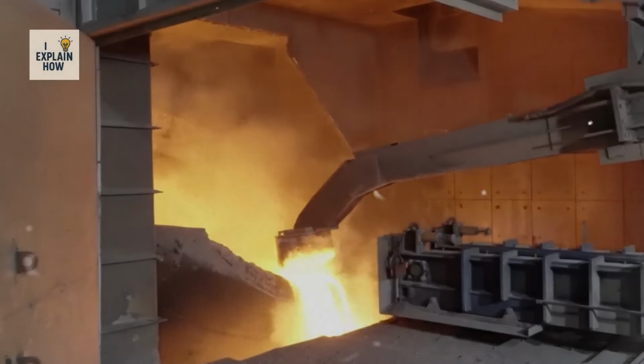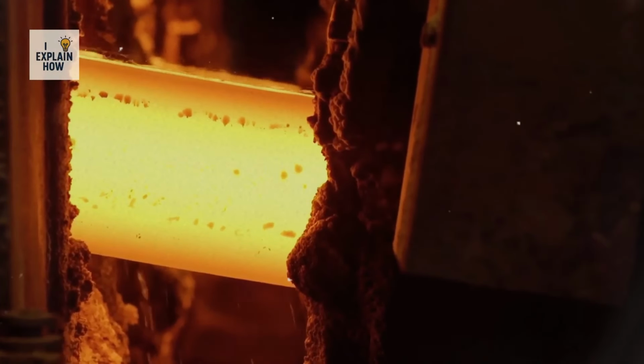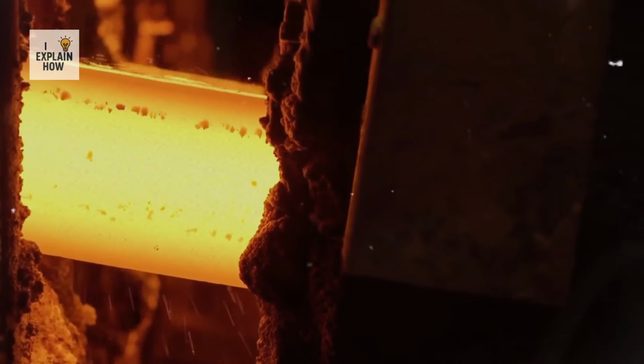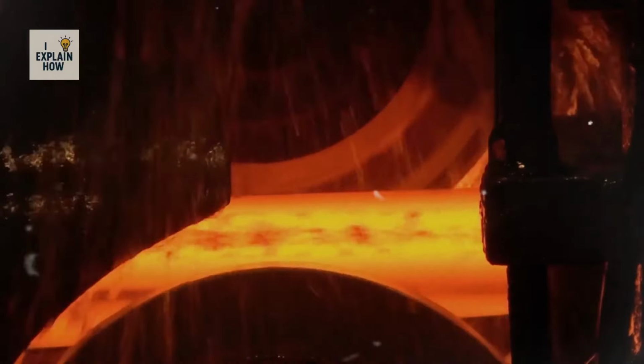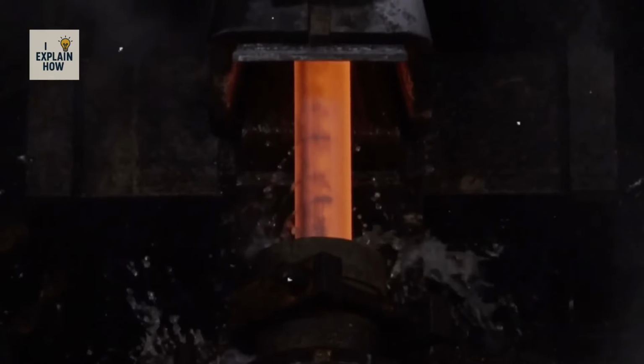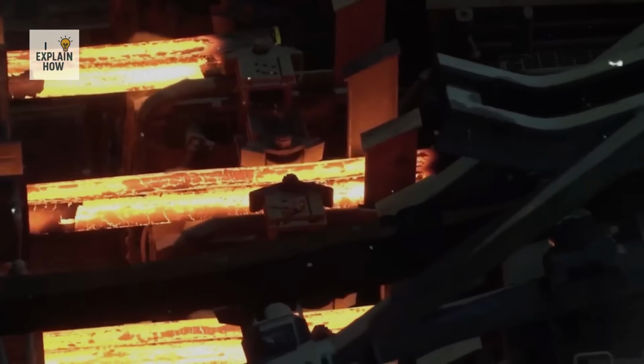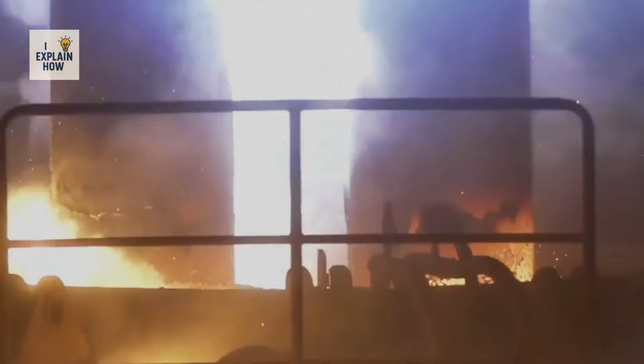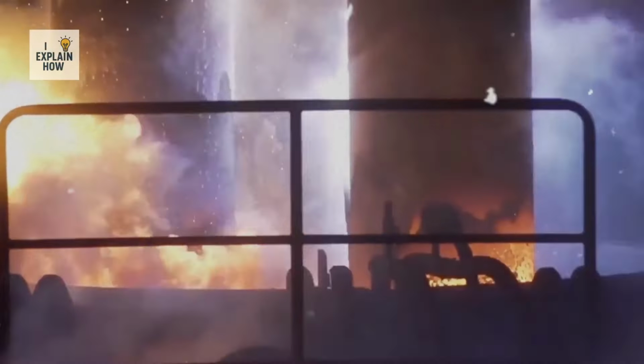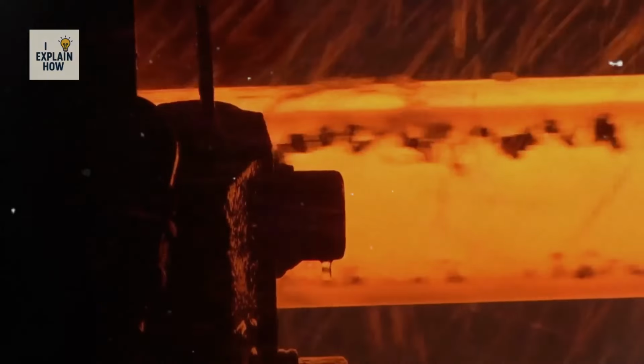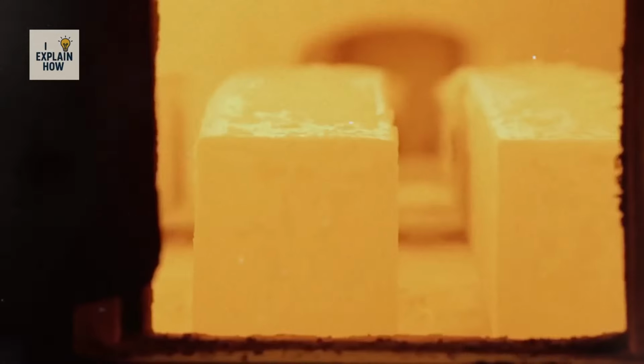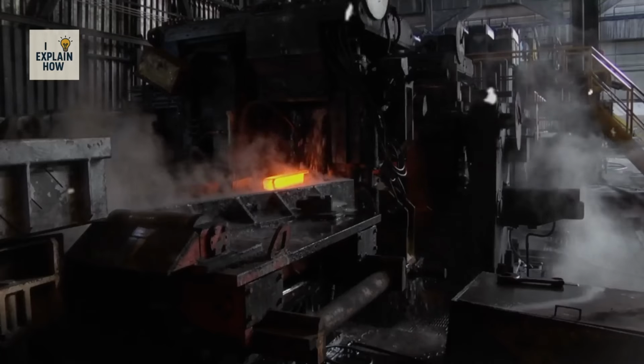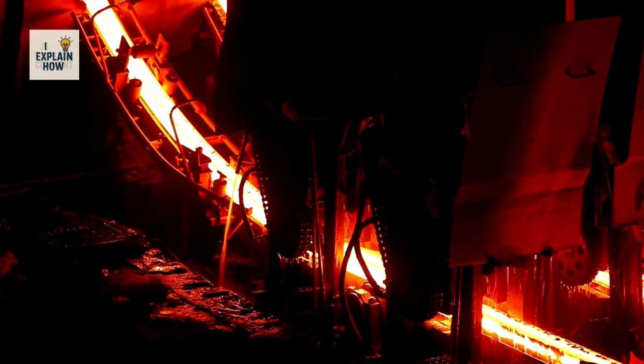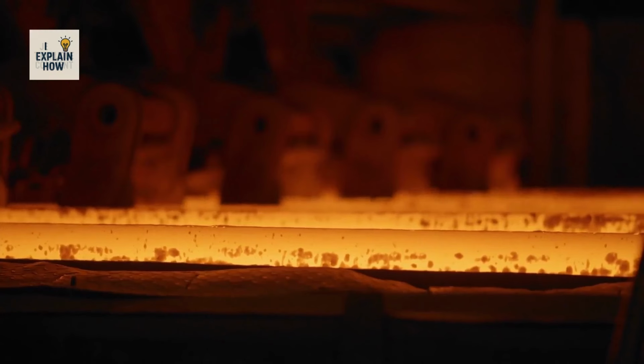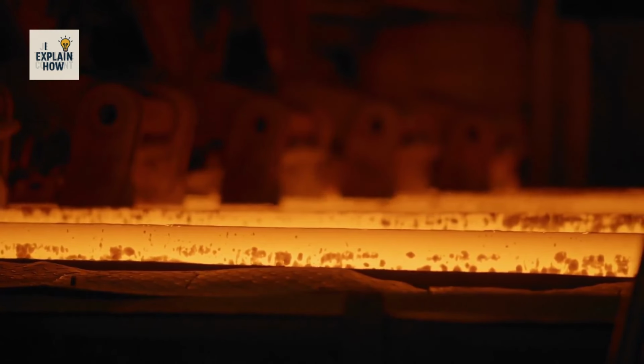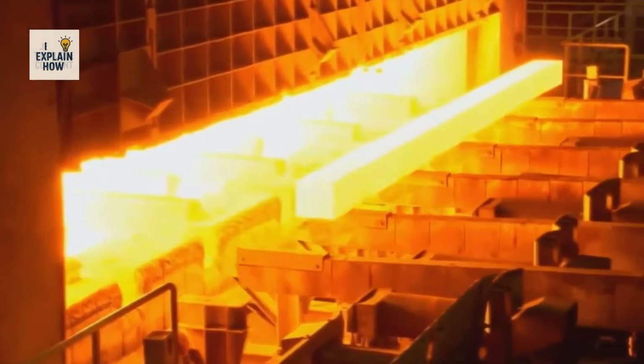Once the steel is purified and its composition adjusted, it moves on to the continuous casting stage. Unlike in the past when the metal was poured into water, today it flows continuously into copper molds cooled by circulating water. Upon contact with the cold walls, the outer layer immediately solidifies, while the core remains liquid. Solidification progresses from the outside to the inside, forming billets several meters long, generally with square or rectangular sections. Upon leaving the mold, still heated to thousands of degrees, they are sent directly to the primary rolling mill to take advantage of their residual heat.